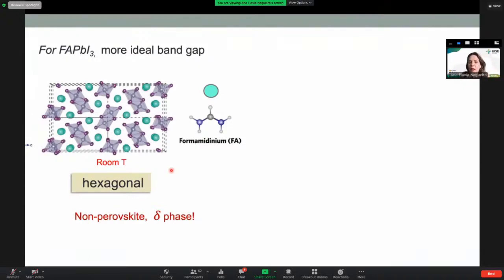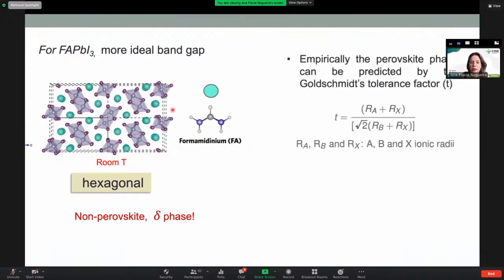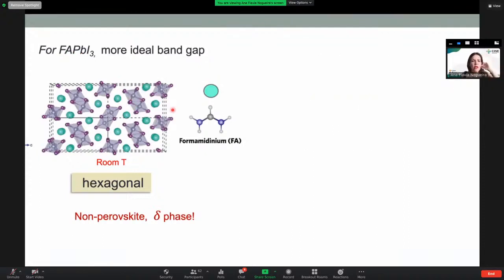So many efforts nowadays are aimed at stabilizing these perovskites not in the hexagonal form, but in the cubic. So I think it's also important to explain why we are mixing many different cations in the A site: methylammonium, formamidinium, cesium, rubidium. Why do we have to work nowadays with multi-cation perovskites in order to achieve this 25% efficiency?